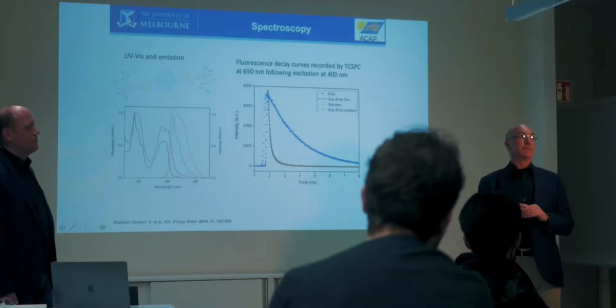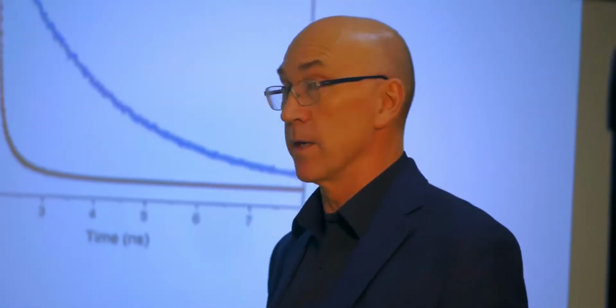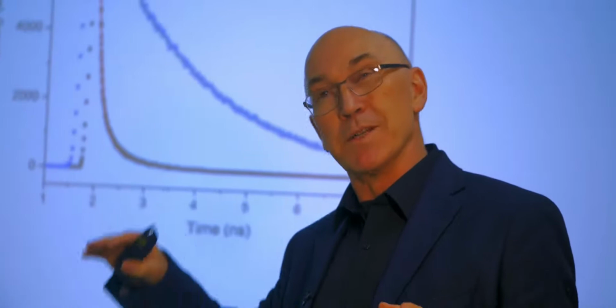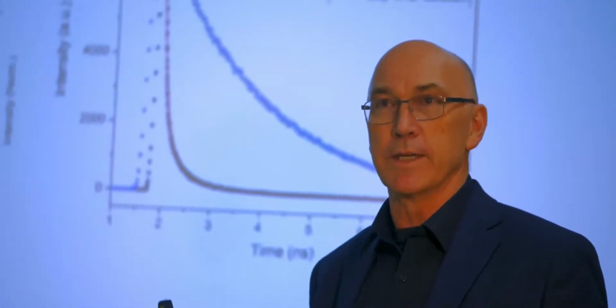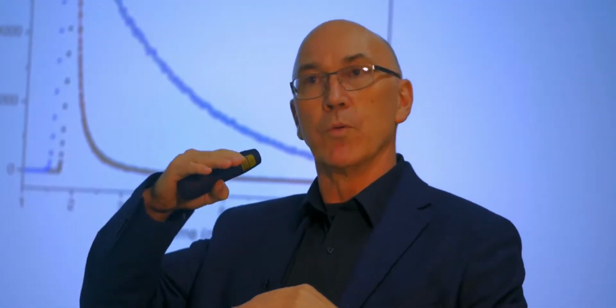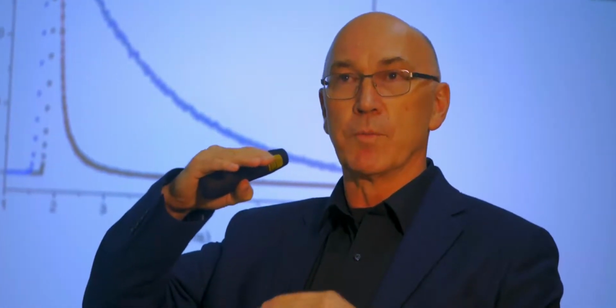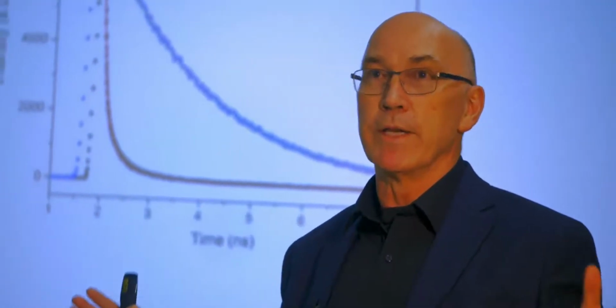Pentacene we don't use because it's air sensitive and it doesn't have enough absorption anyway. All of the chromophores that we've been looking at, and so for example in this, the diketopyrrolopyrrole, this one's got a slightly lower energy, but it should potentially sensitize oxygen. It doesn't. We're now looking at ones where we have 1.2 eV triplet energy levels, and we do everything in air.